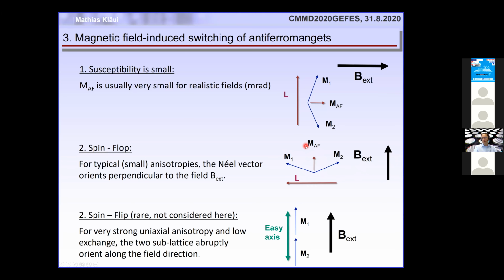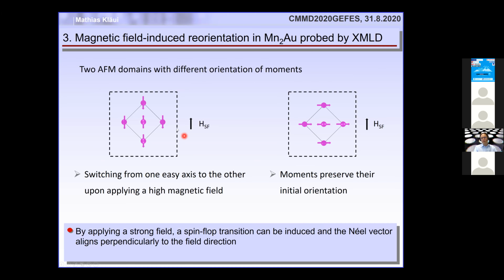And finally, just for the sake of completeness, while we don't look at it here, there is the so-called spin flip. If you have low exchange but strong uniaxial anisotropy, you can get the two sublattices to align ferromagnetically, and that's something, for instance, in the 2D magnets that can happen. Now, I already told you that if you have such a sublattice and you apply a field, then they will orient in a direction which is perpendicular to the applied field.